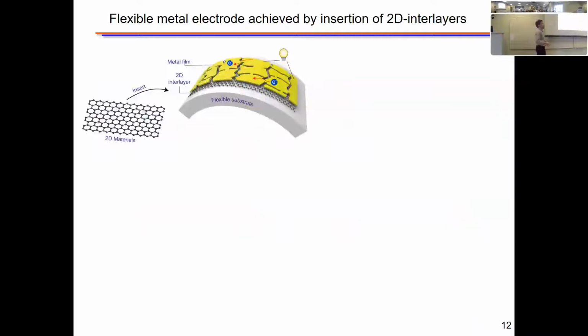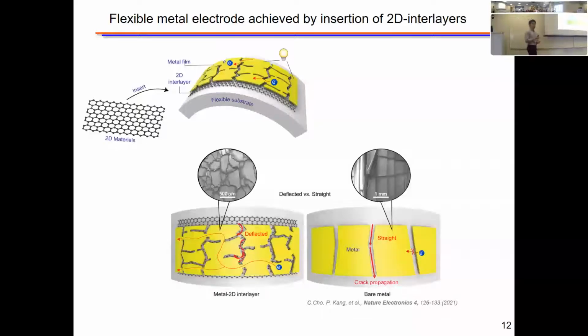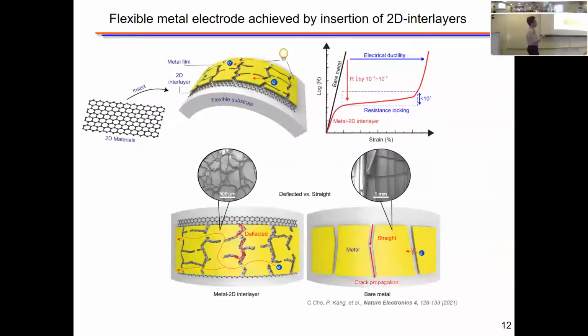To address these challenges, we started with a relatively simple idea. Why don't we just insert 2D materials, because we know they are high strength materials with high toughness? Then the result turned out to be much more interesting than that. We observed strikingly different cracking patterns with the underlying graphene layer, shown in the bottom left schematic, compared to conventional metal on the right. It was really intriguing to see how this microscale phenomenon of crack behavior, or crack modulation, can contribute to the macroscale electrical performance as shown in the plot.